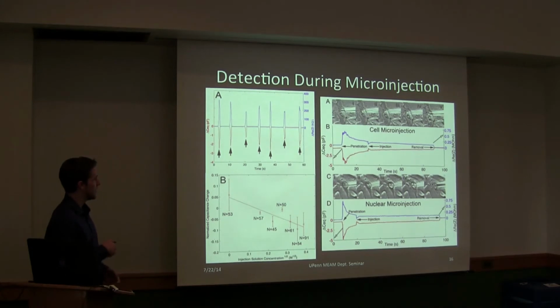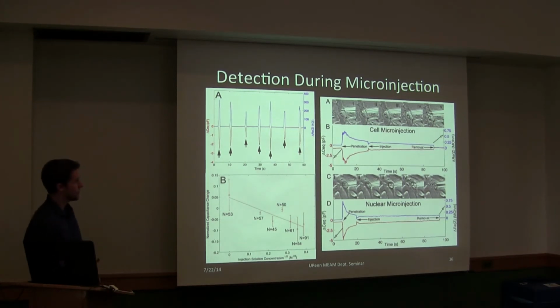So as you can see, we get a several picofarad drop in capacitance, which is quite large, that allows us to very robustly detect penetration during microinjection. We can also look at the normalized capacitance change as a function of the solution concentration. Here we have it to the 1/2 power due to the trends we would expect from the literature. And we roughly get an increasing change in capacitance with increasing concentration. So we can characterize the magnitude of the signal and how it relates to the solution we're injecting into cells.